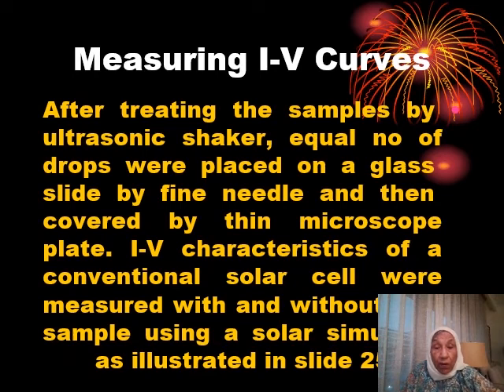So we also measured the IV curves after treating the samples by ultrasonic shakers. Equal number of drops were placed on a glass slide by the fine needle and then covered by a thin microscope plate, and the IV characteristics of the conventional solar cell were measured with and without adding the nano samples we prepared previously.